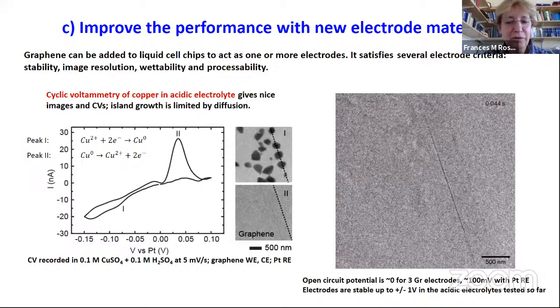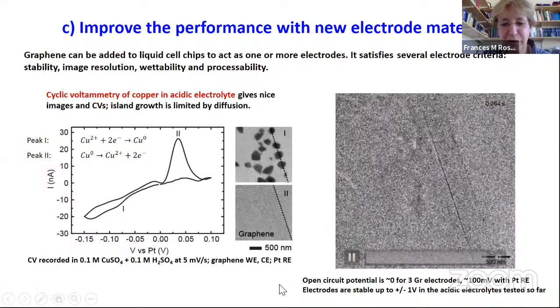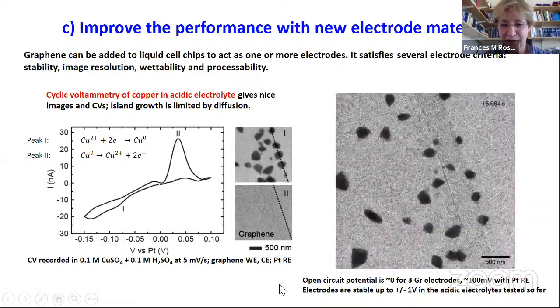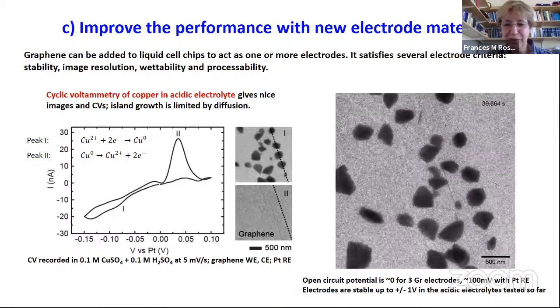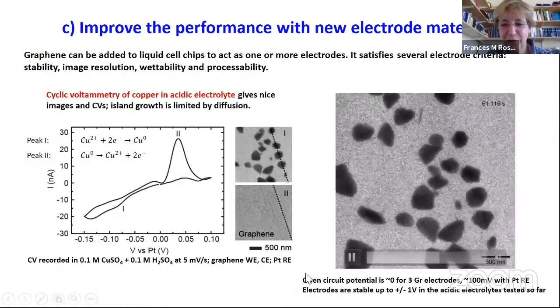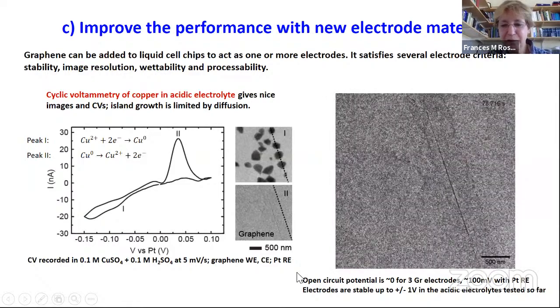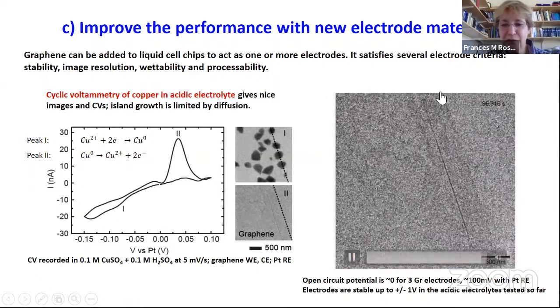We also could look at improving our electrode. Sometimes you don't have a choice, but sometimes you could change the electrode material. And obviously, the thinner it is, the better contrast the growing objects will have, the less dose you'll need to image them. Everything will be much better. So I'm showing you now a movie of copper growing on a graphene electrode. Notice a few things about the movie. It's very noisy because we're using low dose. It's got very low contrast for the electrode, which ends here.